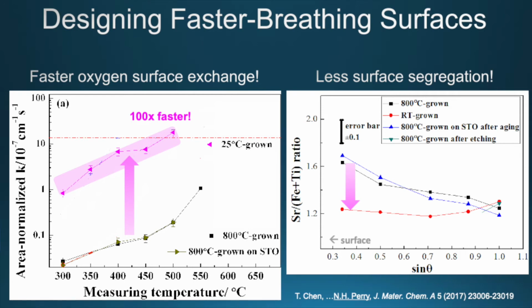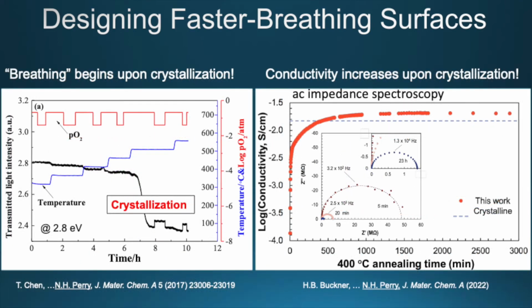So if we look at that, we see in the samples grown at high temperatures, they have this segregation problem. The element that comes out of these samples is strontium. And so we have extra strontium at the surface. But our materials that are grown at low temperatures, they don't have that problem. So their surfaces are much better chemically. So that's great. But there are other reasons for this good behavior as well. It's not just that the surface is nice and pristine.